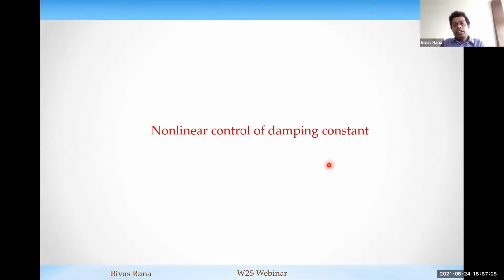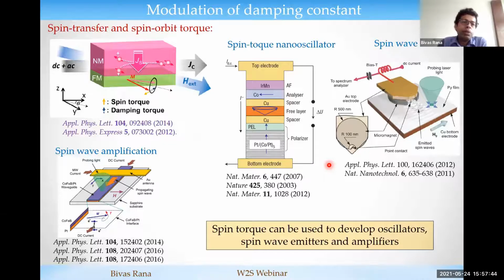Then the important study we did: the nonlinear control of the damping constant. Controlling the damping constant in the ferromagnetic material is very important, because traditionally people use spin transfer torque or spin orbit torque to tune or reduce the damping in the system so that people can amplify the spin wave. People can make a spin torque nano oscillator, and in certain conditions this nano oscillator can even emit spin waves.